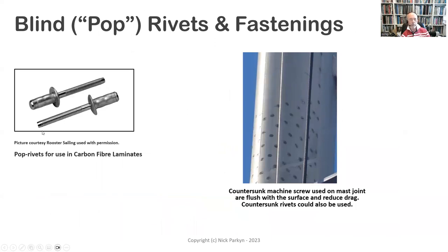They're also, interestingly enough, they have created pop rivets for use in carbon fiber laminates. Now, typically, with carbon fiber laminates, you would not use a standard type pop rivet, because it overloads the surrounding area as you pull it up, and actually causes damage to the area around the rivet hole.